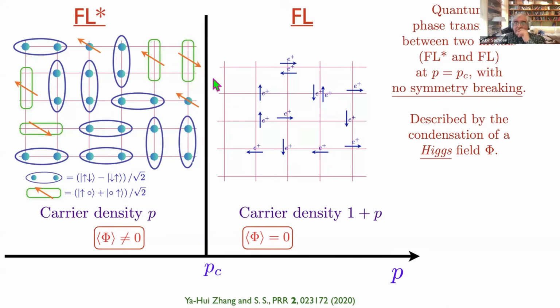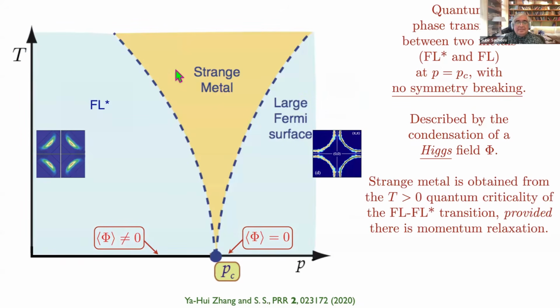There's been an enormous amount of work, and many of the earlier papers, I did not get it right. And the reason is that you may have lots of criticality and lots of scattering, but if this is happening from low energy processes, you will conserve the total momentum. So in fact, you need additional sources of momentum relaxation beyond just taking the continuum theory of the Higgs transition. And that's something that has been clear for a while, but also not clear in many other investigations.